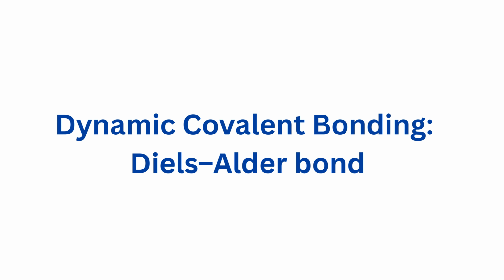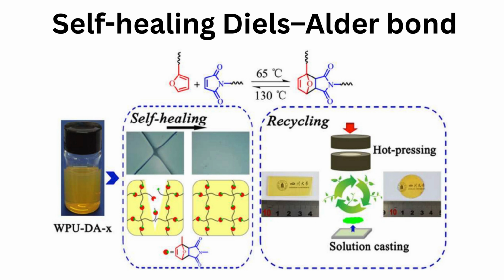Dynamic covalent bonding. Diels-Alder bond. DA bonds are formed through an addition reaction of an olefin with a conjugated olefin, which is a 4+2 cycloaddition reaction. The fabrication of self-healing materials based on DA bonds is achieved by means of temperature control, which results in the breakage and reorganization of DA bonds, thereby imparting self-healing properties to the materials. Scientists introduced dynamic amine-DA bonds into the polymer backbone with a view to preparing a thermally driven, self-healing waterborne polyurethane film based on the DA fracture reorganization reaction.